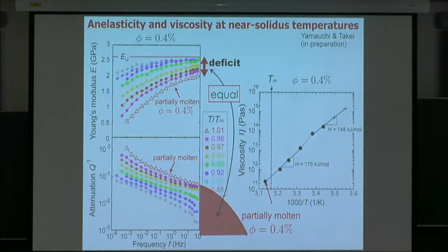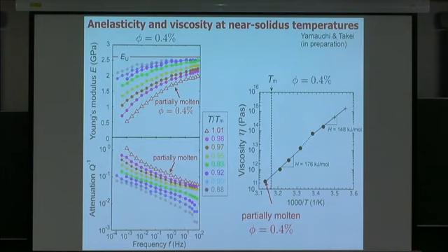So, for each spectrum, although the detailed shape above 100 Hz is unknown, the integral above 100 Hz is known from the modulus data. And this information can be used to constrain the total relaxation strength of the peak dissipation even without any data points above 100 Hz.